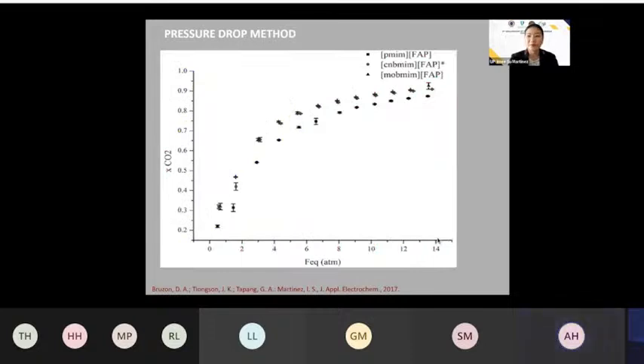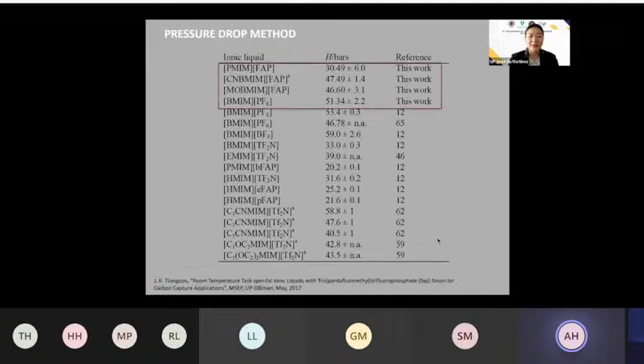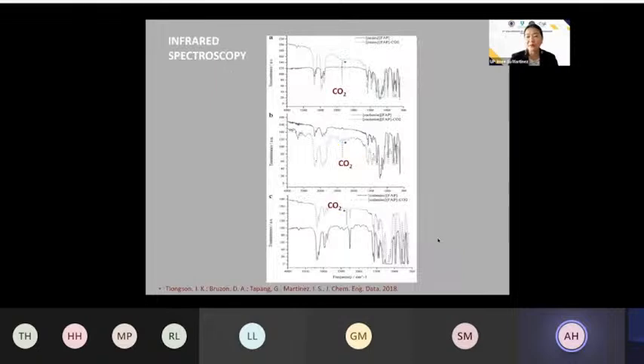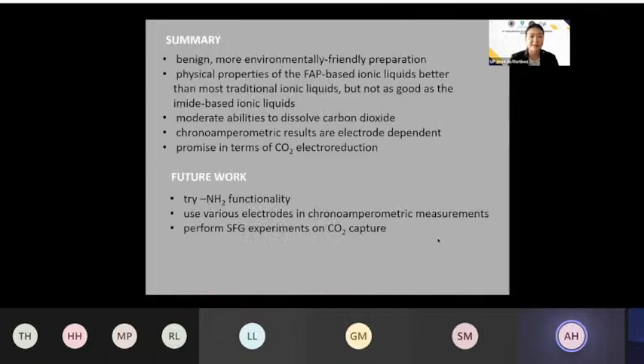And so for the pressure drop method, we also use this to determine the Henry's constants in our ionic liquids. And as you can see here, we get very good results. Of course, comparing it to the imid, you can still see that imid is still higher, but in a way, we are getting very good values for our ionic liquids. And then we also perform IR spectroscopy just to see if there is really carbon dioxide in our ionic liquids. And as you can see, among the three ionic liquids, you can definitely see that carbon dioxide is present.